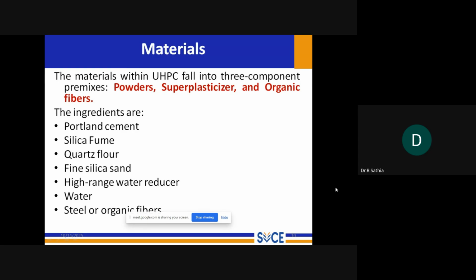Next, the coarse aggregate is replaced. So now we have eliminated the coarse aggregates. How does the strength get achieved, and how are we going to achieve this dense packing? The coarse aggregate is replaced by a well-graded fine sand to ensure high packing order. This UHPC mix design incorporates two different types of chemical admixtures, namely high range water reducing admixtures and concrete setting accelerators. Finally, micro-sized steel fibers are incorporated to increase the strength and the ductility.